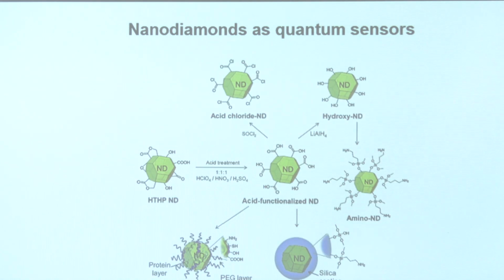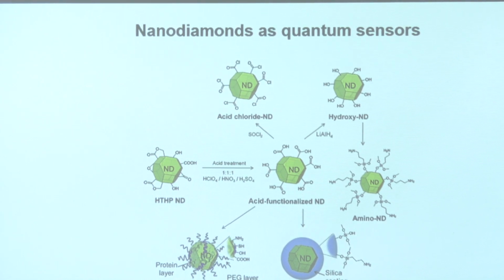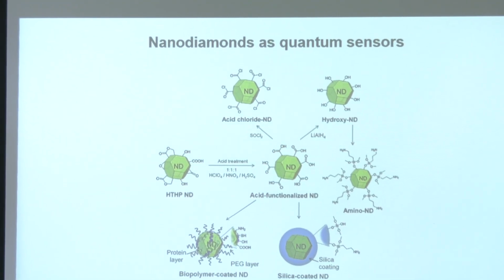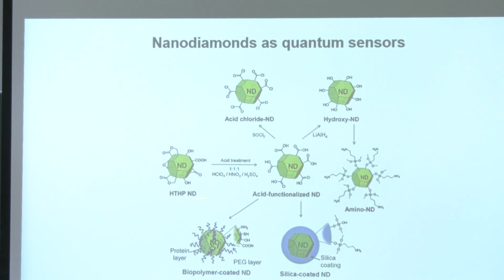The second important point is that you need to functionalize your diamonds, so they should target some proteins. They should go to some place in the cell of interest. And so there's another big effort in actually making suitable chemical groups on top of diamonds. Diamond is usually an inert material, so it's not very easy to create suitable groups, and this is an active field of research. I mentioned before amino groups that can link to some proteins. Carboxy groups are also used, and in some cases biopolymers are used to create a large number of groups, where you fold your diamond inside of a kind of biopolymer mass.